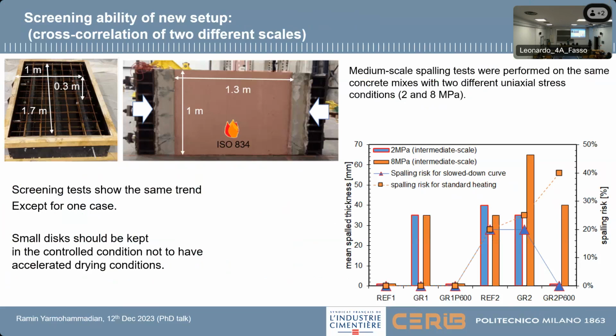But the issue is when we are using a small sample, we should know how much moisture we still have in these small samples. They are not the same actually, because if we keep a small sample and a large sample in the same condition, the small sample, since it has a larger surface, is gonna dry earlier. So we should have the same initial moisture.